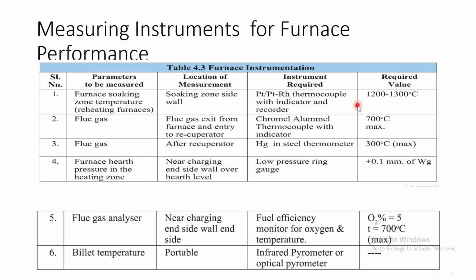So that is how the thermocouple, a combination of dissimilar metals like platinum and rhodium, is used for measuring the soaking zone temperature, and the soaking zone temperature is in the range of 1200 to 1300 degrees centigrade. This is how furnace soaking zone temperature has to be measured.